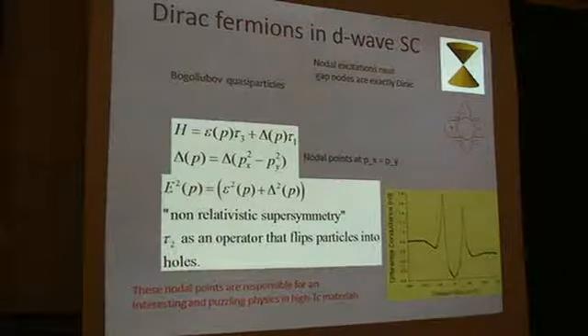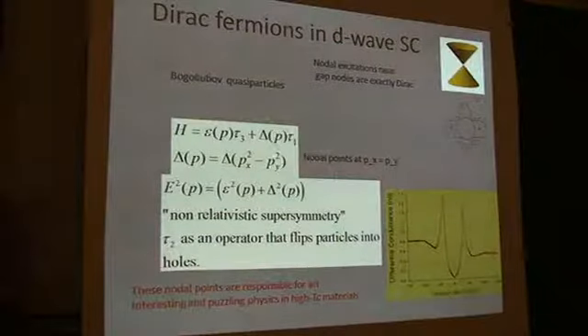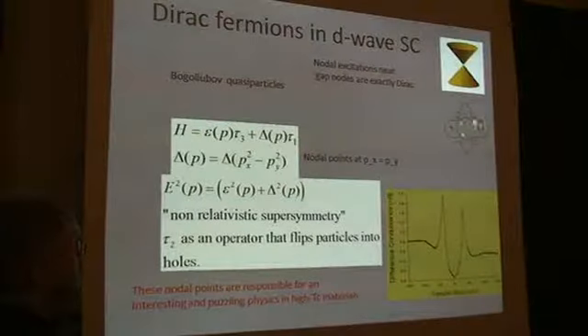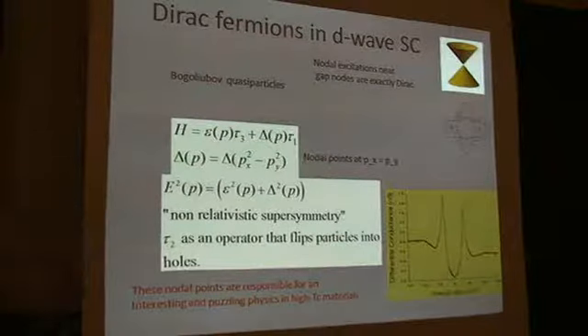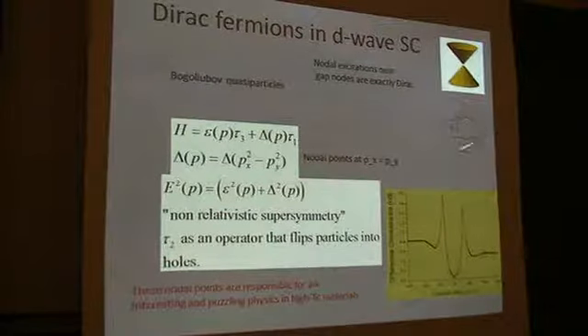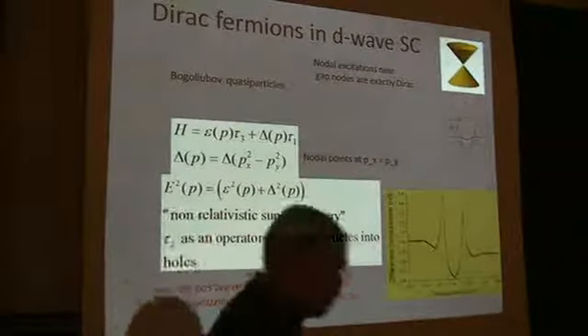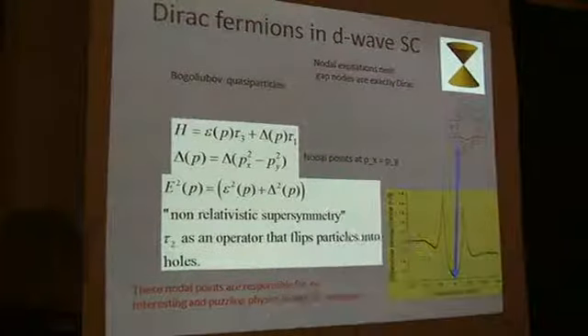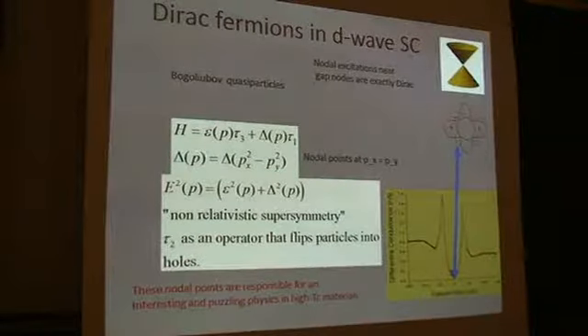If I write down the Bogoliubov-de Gennes equation, I have a diagonal piece, which is the quasi-particle energy, and an off-diagonal piece, which is the gap. Because I need to go from plus to minus while keeping the gap real, there will be points along this two-dimensional Fermi surface where the gap vanishes, and at the same time, at the Fermi surface, the energy vanishes. So there is a set of four nodes in a d-wave superconductor, which is a source of all sorts of infrared, low energy physics that is very, very interesting. A number of people here in the audience spend time looking at those. You can view it as a pathology because it doesn't give you a full degree of protection, not a full gap state, but at the same time, you can view it as a very interesting piece of physics.